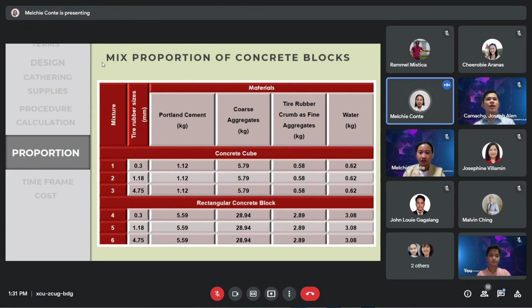In order for us to make one piece of concrete cube, we need 1.12 kilograms of cement, 5.79 kilograms of gravel as coarse aggregates, 0.58 kilograms of tire rubber crumb as fine aggregates, and 0.62 kilograms of water. While in making one piece of rectangular concrete block, we need 5.59 kilograms of cement, 28.94 kilograms of gravel as coarse aggregates, 2.89 kilograms of tire rubber crumb as fine aggregates, and 3.08 kilograms of water.